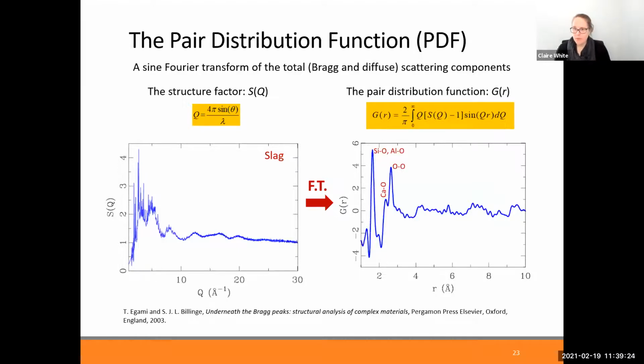Most of you are probably aware of the technique of PDF analysis, but just in case you're not, it's a diffraction-based technique. So you're doing either X-ray or neutron scattering. You're collecting over a very wide Q range, momentum transfer. It's very important for getting good PDF results. And then you're just Fourier transforming the data. And so you're going from reciprocal space to real space, same information, just displayed in different spaces.